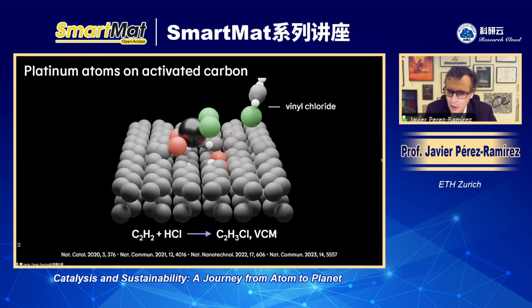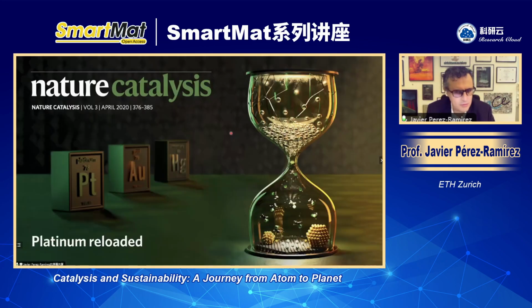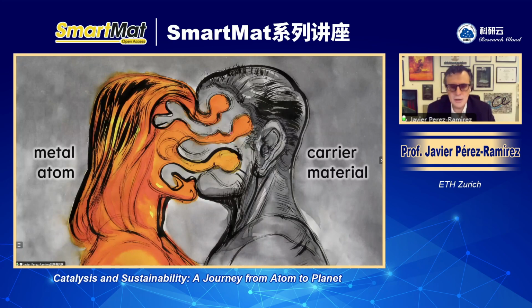And very often it is conceived that the single atom is doing the whole job, but in single atom catalysis, the carrier is not just the stabilizer of the single atom. Very often it has a co-catalytic role, and therefore it has to be designed accordingly. In this case, the catalytic role is adsorption of acetylene. The platinum single atoms for acetylene hydrochlorination were reported in 2020 in Nature Catalysis. And what I want to emphasize again is that when you design a single atom catalyst, you have to take care not only of the metal atom and its environment, but also of the structure of the carrier material. Because the carrier material is not just a carrier, it has a catalytic function most of the times.